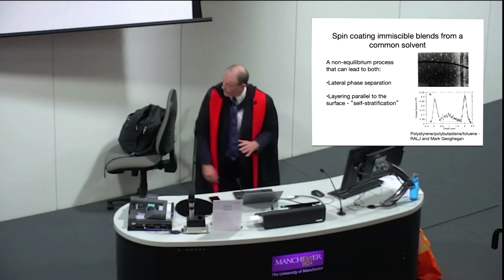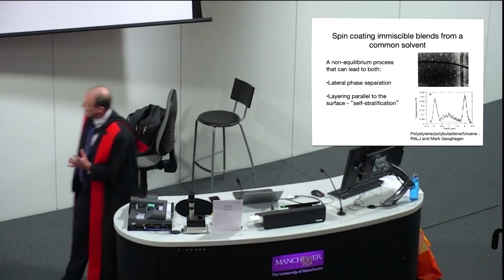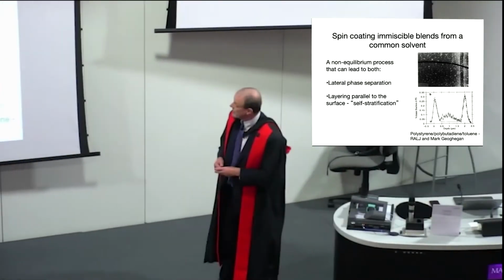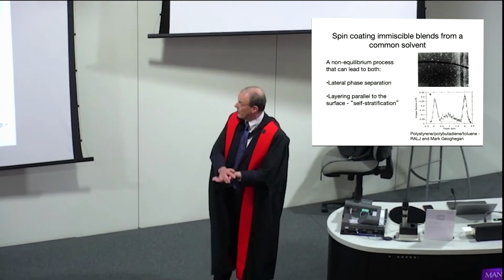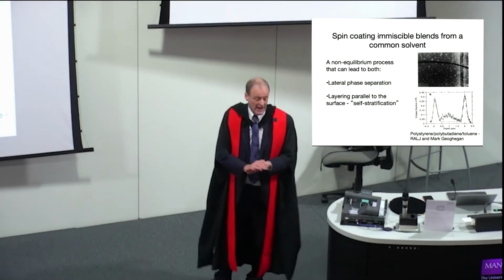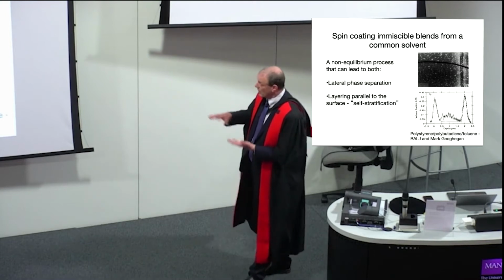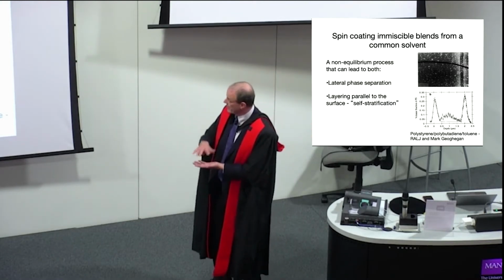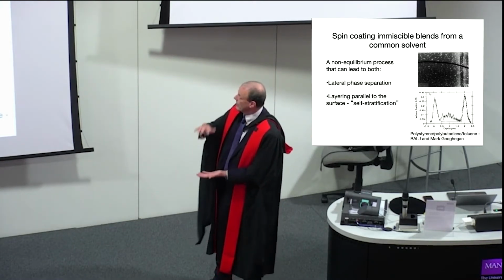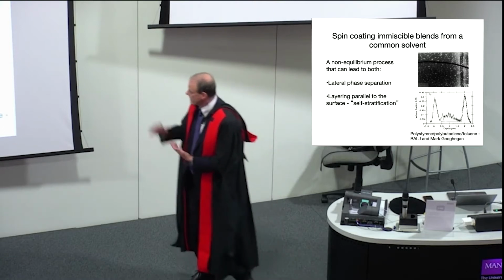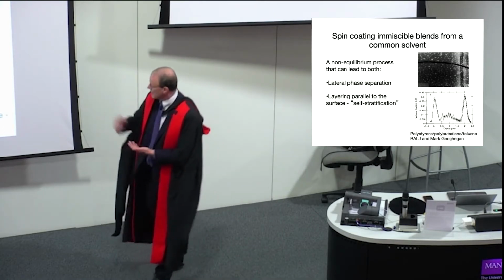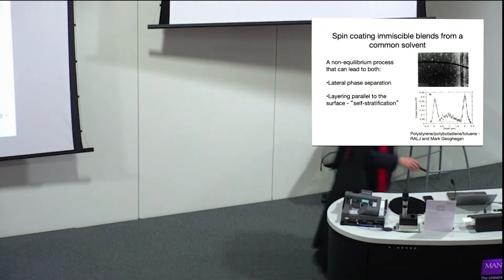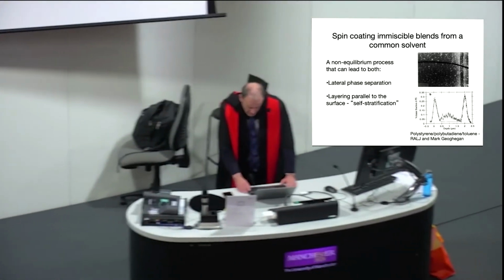So, for example, found in this very simple case: you take two polymers, mix them in a solvent, and spin coat them. What do you get? What you get can show two things. You can get phase separation in the plane, but you can also get this layering parallel to the surface, so-called self-stratification. Mark Geoghegan was one of my early students who showed this.